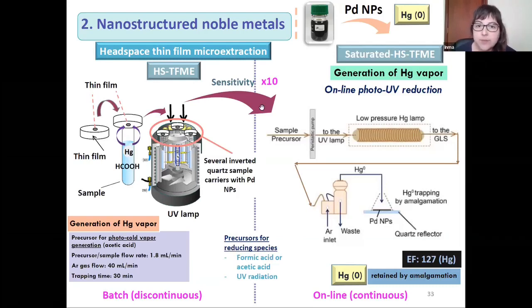This system can be improved, especially the sensitivity by a factor of 10, as we can see with the online method. In this case, the sample solution and the precursor, which are very similar, formic acid or acetic acid. Finally, we use acetic acid because it's less toxic than formic acid. The sample and the precursors are moved through a peristaltic pump to the ultraviolet lamp, generating the vapor of mercury, which moves to the gas-liquid separator and is trapped in the same system as described in the previous slide, in the palladium nanoparticles.